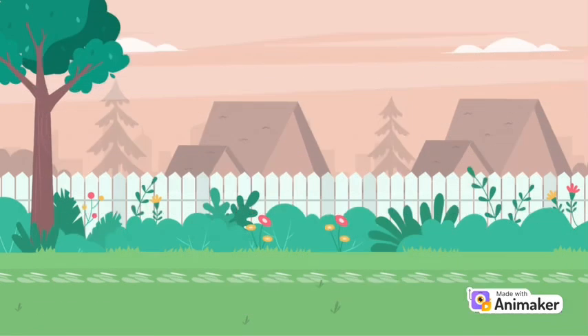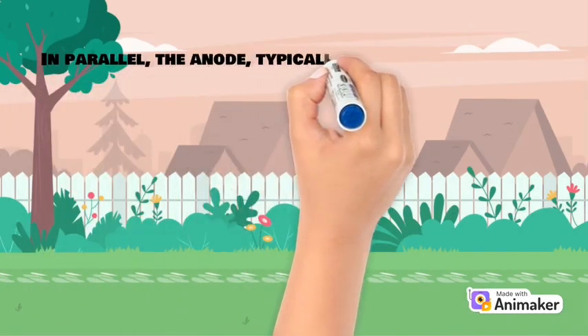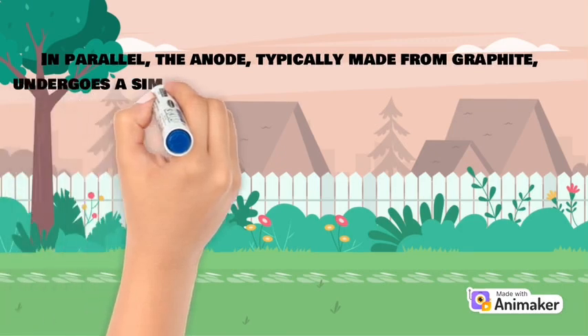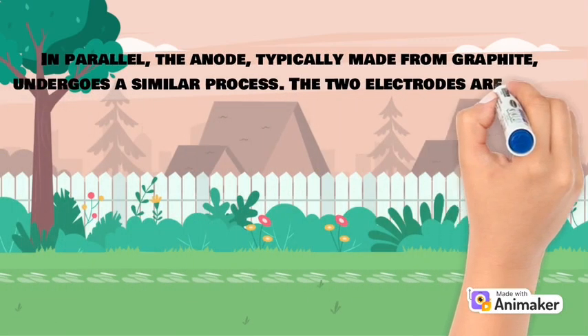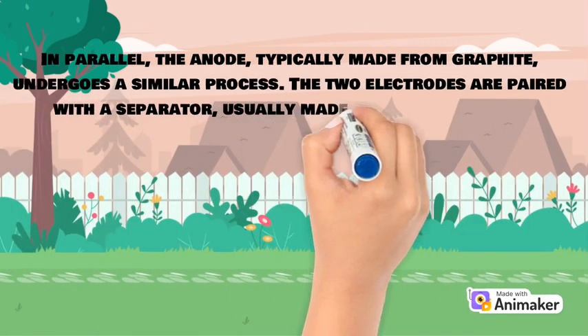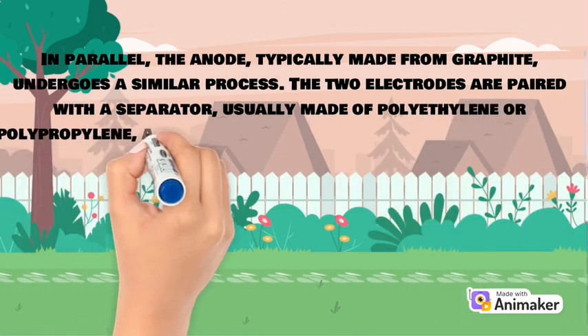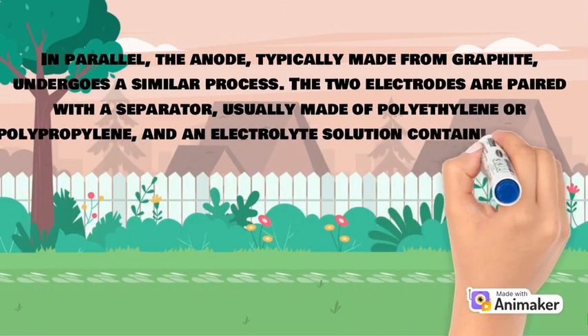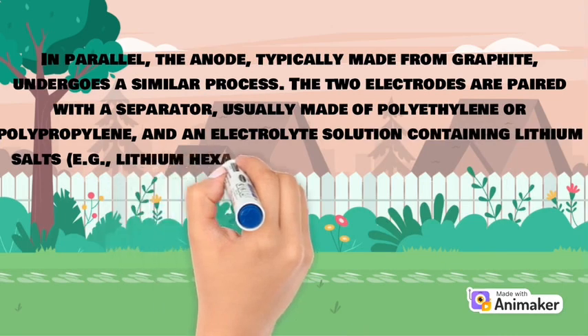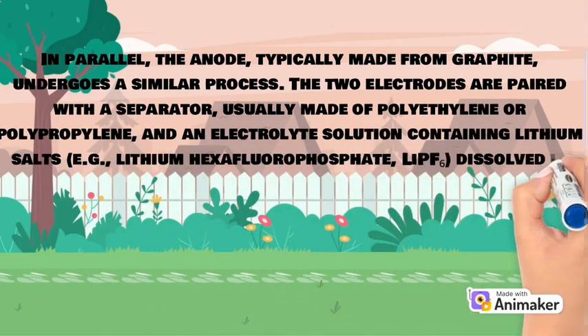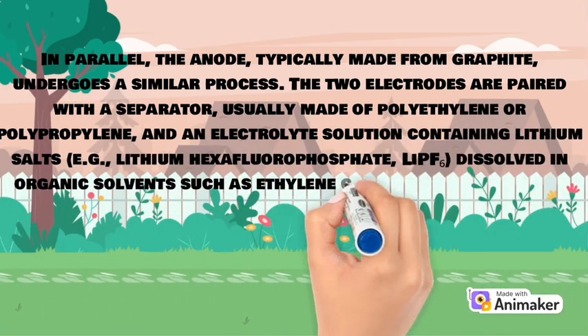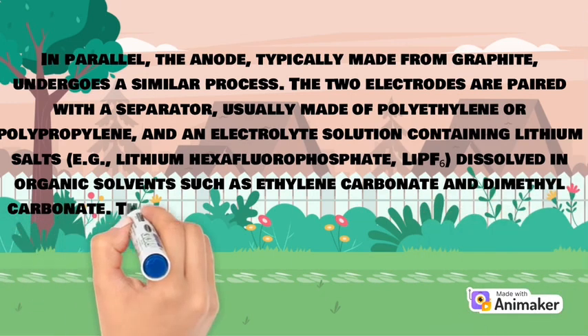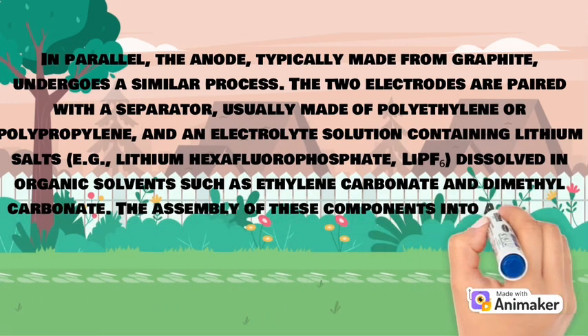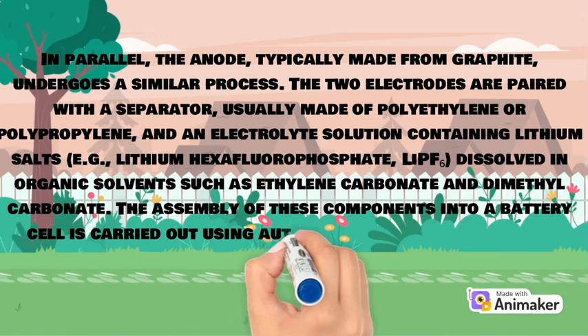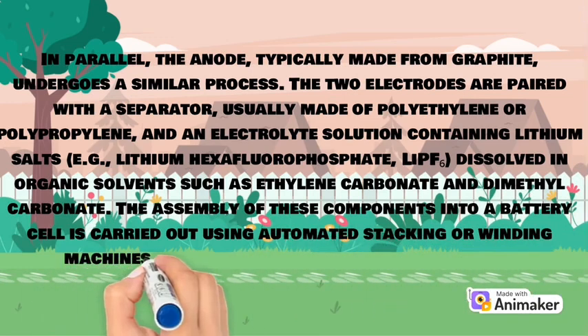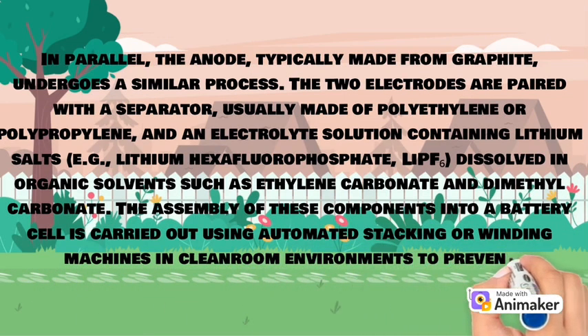coated film. In parallel, the anode, typically made from graphite, undergoes a similar process. The two electrodes are pressed with a separator, usually made from polyethylene or polypropylene, and an electrolyte solution containing lithium salts dissolved in organic solvents such as ethylene carbonate and dimethyl carbonate. The assembly of these components into a battery cell is carried out using automated stacking or winding machines in a clean room environment to prevent contamination.